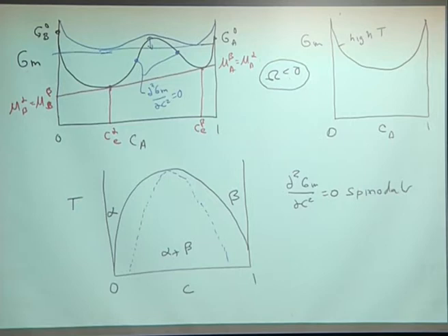The spinodals and the actual phase compositions come to the same point at the critical point at the top here. I don't want anyone to get confused: these dashed lines are not phase boundaries, but they're put on there as a guide to the eye for the limits of metastability, and we'll talk a little bit about what that means. They tell you something about the free energy functions that are given here.